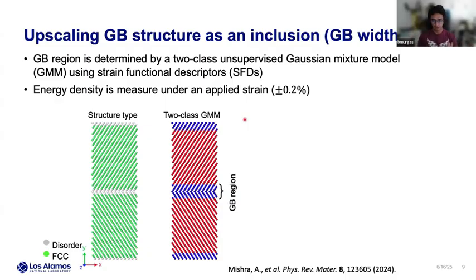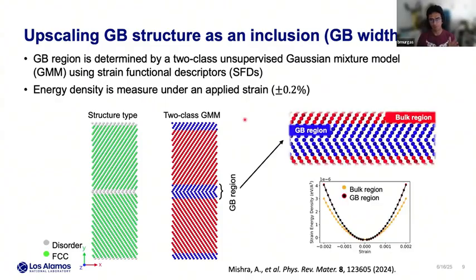After we define this grain boundary region, we now have the width of my grain boundary region, and we apply a strain. When you apply a strain, you can also compute the energy of your bulk region and your grain boundary region. And as you apply a higher strain, in positive or negative values, you will see that your energy gets farther away.